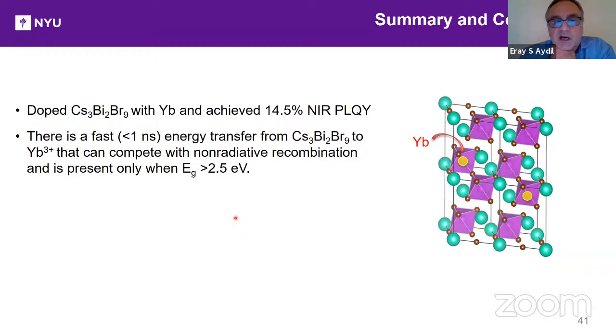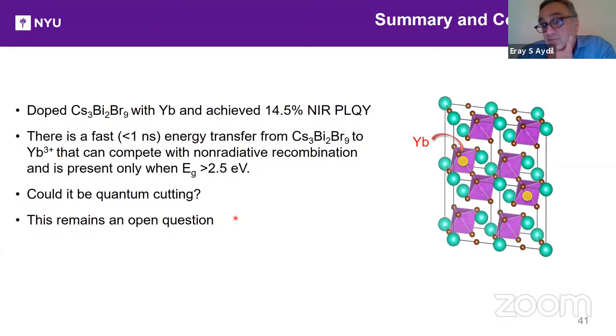And there is a fast energy transfer from the cesium-3 bismuth bromide bands to ytterbium 3+ ions that can compete with non-radiative recombination. And it's only present when the band gap is greater than 2.5 electron volts. So could it be quantum cutting? It is still an open question.